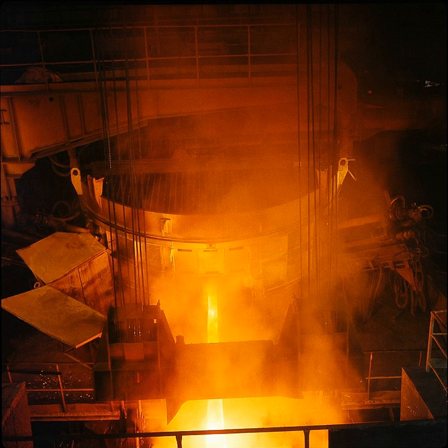The electrodes are lowered onto the scrap, an arc is struck and the electrodes are then set to bore into the layer of shred at the top of the furnace. Lower voltages are selected for this first part of the operation to protect the roof and walls from excessive heat and damage from the arcs. Once the electrodes have reached the heavy melt at the base of the furnace and the arcs are shielded by the scrap, the voltage can be increased and the electrodes raised slightly, lengthening the arcs and increasing power to the melt. This enables a molten pool to form more rapidly, reducing tap-to-tap times.